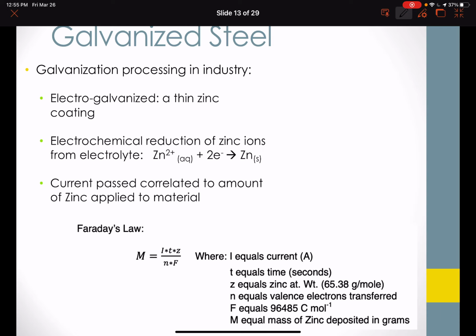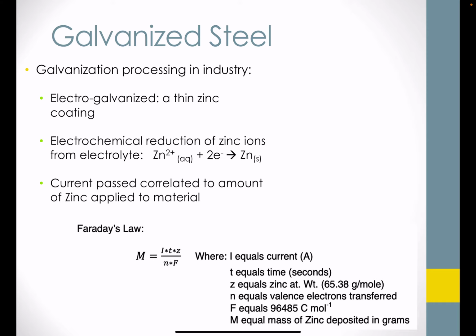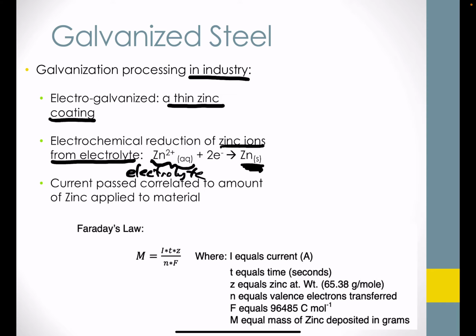Okay, so galvanized steel can be generated from two main methods. The first one that's common in industry is what's called electrogalvanization. This leads to a relatively thin zinc coating on the metal object. And it's generated by an electrochemical reduction of zinc ions from an electrolyte to generate that zinc metal on the surface. Okay, so you can see here zinc ions. This would be found in the electrolyte. They undergo an electrochemical process where they're combined with electrons from the completed circuit to reduce zinc ions to zinc solid as a coating on the metal.